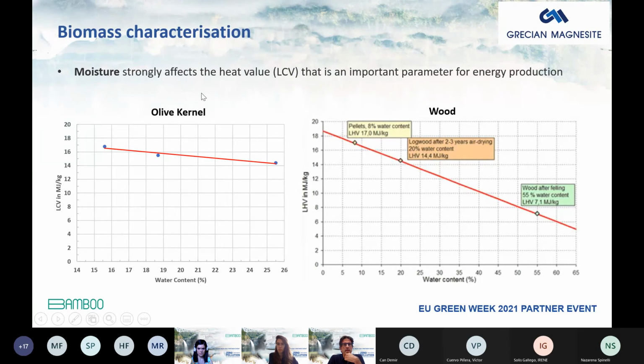As I said, moisture strongly affects the heat value, and this is also an important parameter for energy production. Indicatively, wood can come in all varieties, with biomass moisture as high as 50 or 60%. You see how much the low heating value is reduced. On the other hand, for the olive kernel, where the water content is less, moisture can range from 15 to 25%. Again, there is also a significant reduction in the heating value. Of course, this is as delivered.